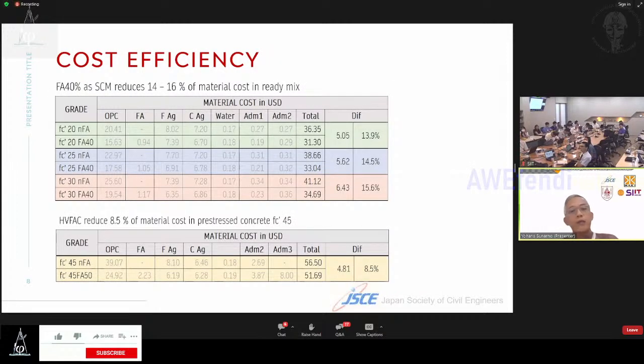So next, I just want to share about our cost efficiency for using fly ash. At the first table, I compare three grades of concrete. The first is FC 20 megapascal. We compare no fly ash with fly ash at 40%. With this comparison, we can see that at FC 20, we can reduce about $5 per cubic meter of concrete, or about 13.9% of the total material cost.